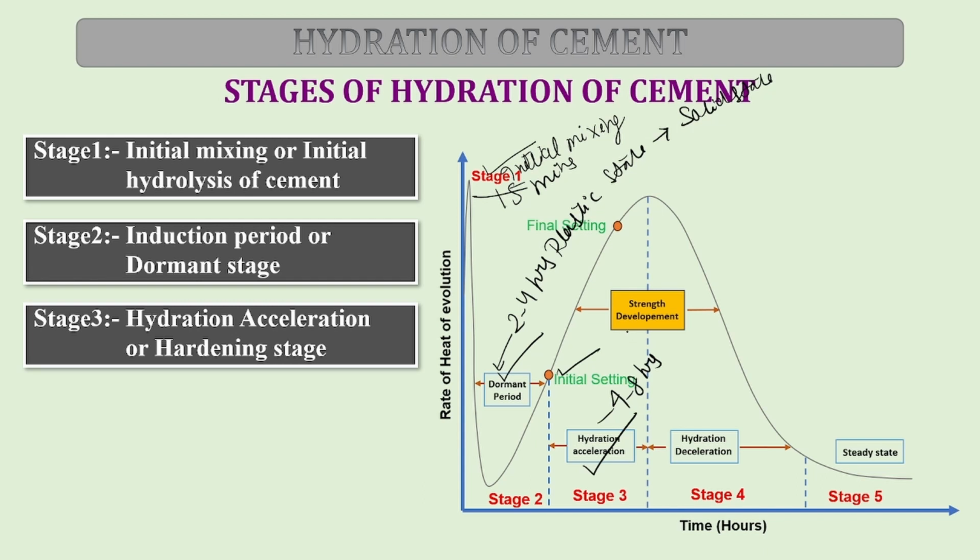So, the two compounds, that is the C2S and C3S, react to form the CSH, that is the calcium silicate hydrate. Now, while using a large volume of concrete, it is essential to keep an eye on internal temperature fluctuations, because the concrete's temperature will quickly increase at this point, reaching internal temperatures of about 70 to 80 degrees centigrade or even higher. Now, it is often recommended that this temperature should be kept below 70 degrees centigrade.